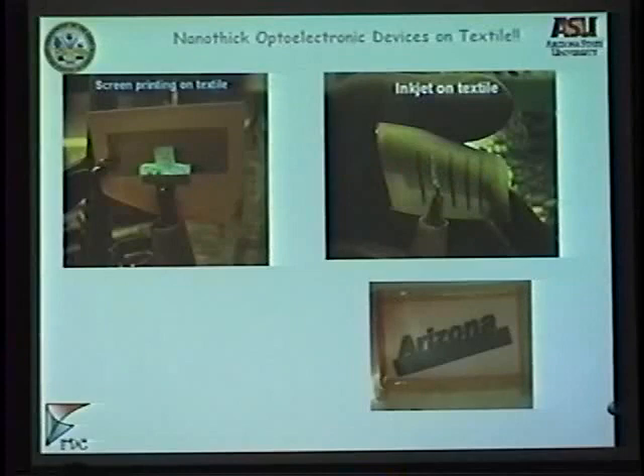So the textile has a roughness. You could imagine the roughness of a shirt. It's extremely high, more than 100 microns sometimes. In order to build this 100 nanometer thick device on top of a 100 micron rough surface, you have to do a lot of surface engineering to make it work. And there's still a lot of challenges.